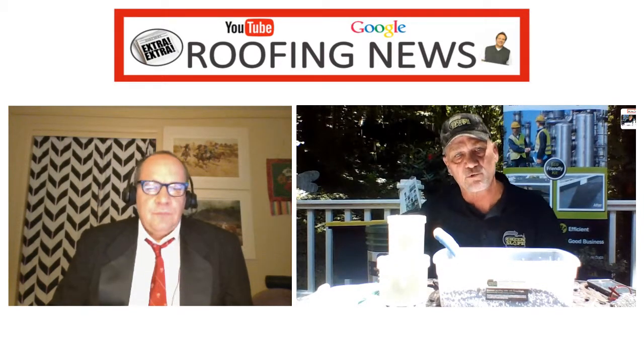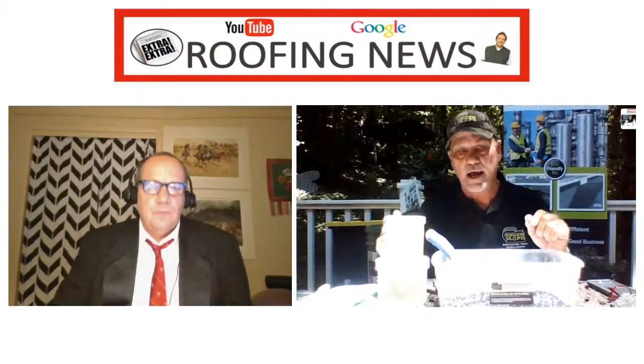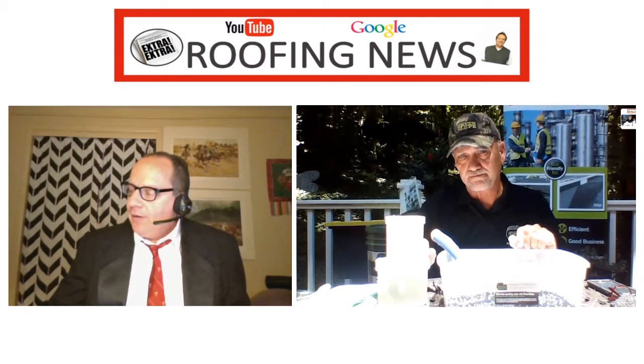We have the kit because a lot of times it's hard to get on the roof. A 5 gallon pail is easy for a service technician to have on the truck and run up. One basic 5 gallon kit covers about 18 square feet at a half-inch depth, which covers a lot of ground. So 18 square feet, and I'm sorry, what was the depth? At a half inch. Very good. So for a 5 gallon, 18 square feet, half inch.